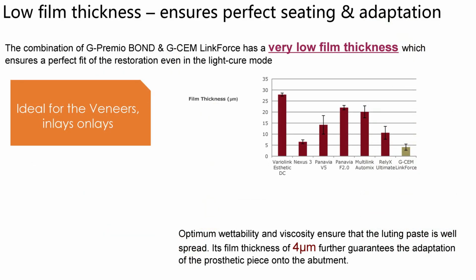So it becomes one cement which caters to all kinds of processes and all kinds of substrates. Now, the advantage of this G-CEM LinkForce Kit is it ensures a perfect seating and a perfect adaptation owing to its low film thickness. The overall film thickness of G-CEM LinkForce adhesive resin luting cement is just 4 microns, which includes the 3 microns of the bonding agent. So this is an ideal luting cement for veneers, inlays, and onlays. Because for veneers, what you require is the least film thickness in terms of the bonding agent as well as the resin luting cement.